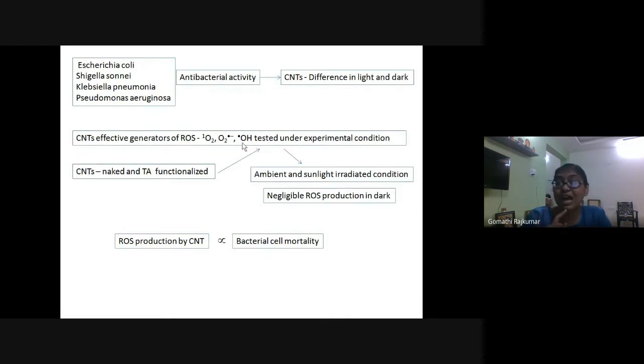And we found out that these oxy radicals were generated in the presence of light. Whereas in the dark, in the presence of water, carbon nanotubes did not generate all these three oxy radicals. So one thing was sure from us, at ambient room condition, in the presence of water and in the presence of sunlight or normal light, carbon nanotubes were capable of oxy radical production. Whereas in the dark, carbon nanotubes did not produce reactive oxygen species.